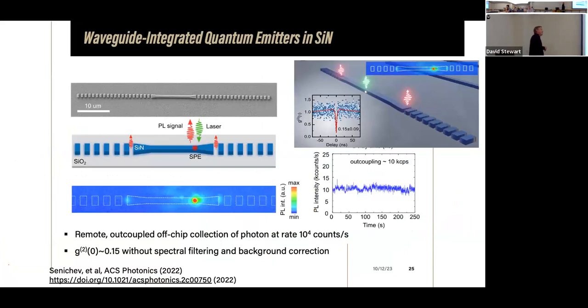But what we already did is we successfully coupled these emitters to a silicon nitride waveguide, like it's shown here. But in this case, we basically randomly chose a waveguide where there is an emitter. So we didn't implant it, we just chose one where there is a single emitter, this defect. We excite it through a grating. So light goes here, we excite through this grating into a single mode waveguide. Then it propagates, excites these single photon emitters, and then we detect the single photon emission.